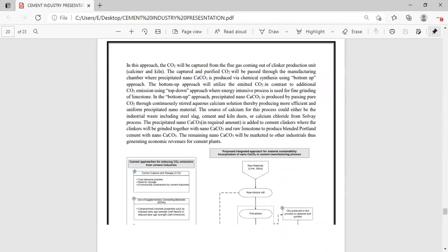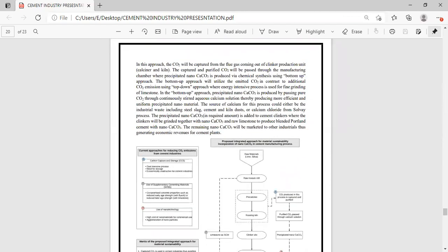In this approach, the carbon dioxide is captured from flue gases coming out of the clinker production unit. The captured and purified carbon dioxide will pass through manufacturing chambers where the precipitated nano calcium carbonate is produced via chemical synthesis using a bottom-up approach. The bottom-up approach will utilize the emitted carbon dioxide, in contrast to additional carbon dioxide emission using top-down approaches where an energy-intensive process is used for fine grinding of limestone. In the bottom-up approach, the nano calcium carbonate is produced by passing pure carbon dioxide through a continuously stirred aqueous calcium solution, thereby producing more efficient and uniform precipitated nanomaterials.